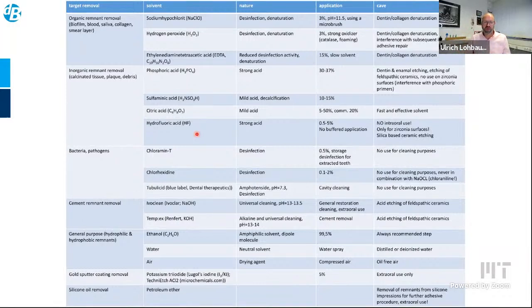So every material has a certain resistance, and there is a list. I won't go through all the solutions, but there is a list of mainly alkaline or acidic or tensidic or alcoholic amphiphilic cleaning agents with different pHs. And those cleaning agents are used for removal of, and this is again important for you as researchers, you need to know where your failed part is coming from. So you need probably to remove biofilm, blood, saliva, any type of organic remnant on the surface. You have hydrogen peroxide or sodium hypochlorite. EDTA is a bit slower than sodium hypochlorite, but this can be used for cleaning organic remnants.